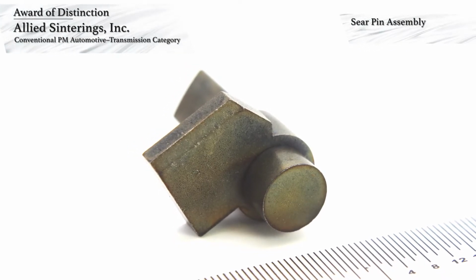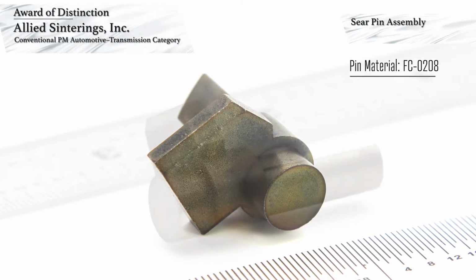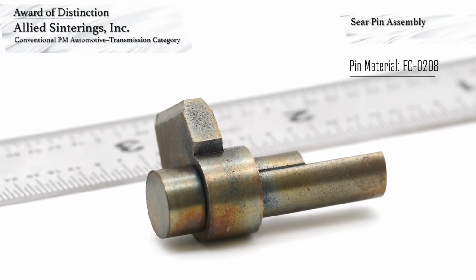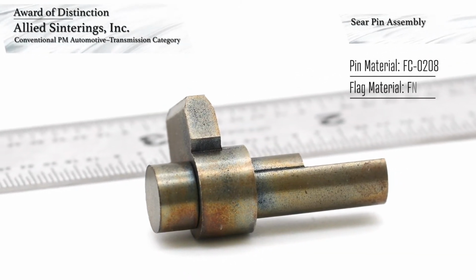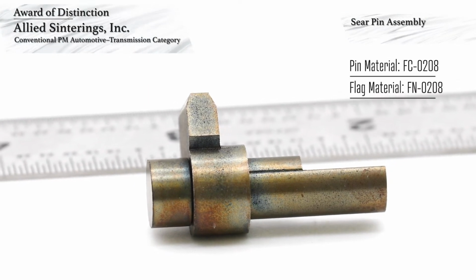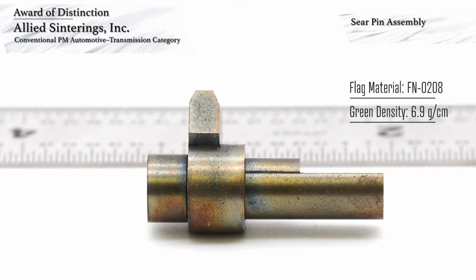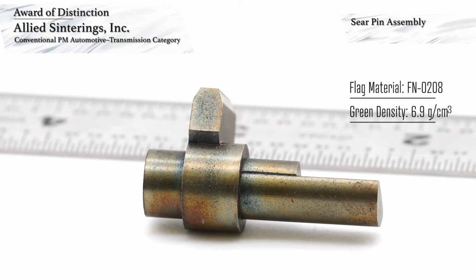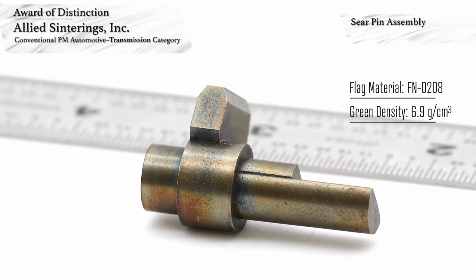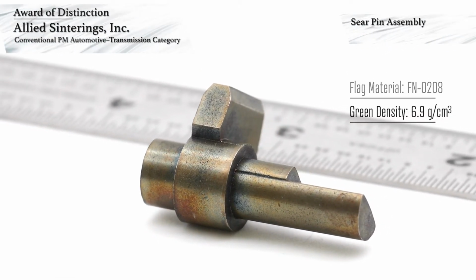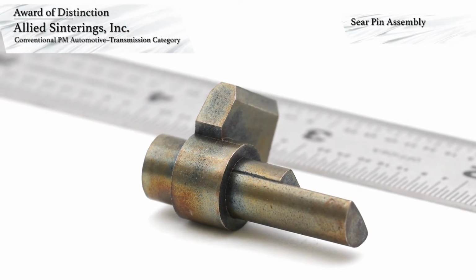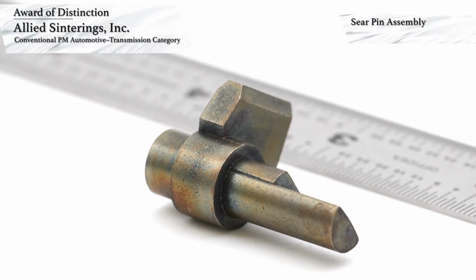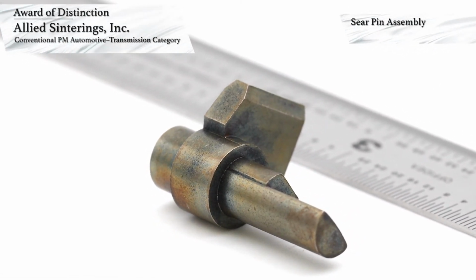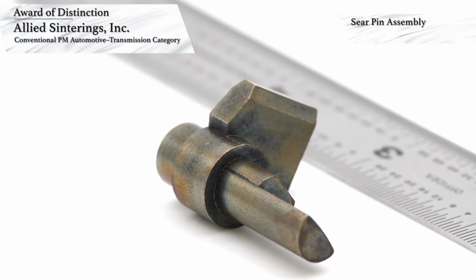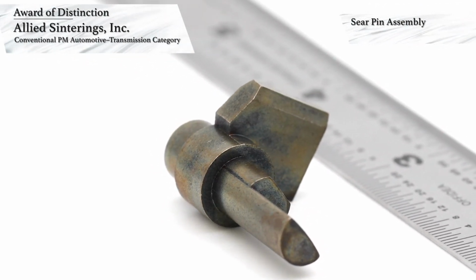The pin is made using FC0208 copper steel and is pressed to a green density of 6.8 grams per cubic centimeter. The flag is made using FN0208 nickel steel and is pressed to a green density of 6.9 grams per cubic centimeter. The copper steel pin grows during sintering while the nickel steel flag shrinks. A push-out force minimum of 445 newtons can be maintained easily.